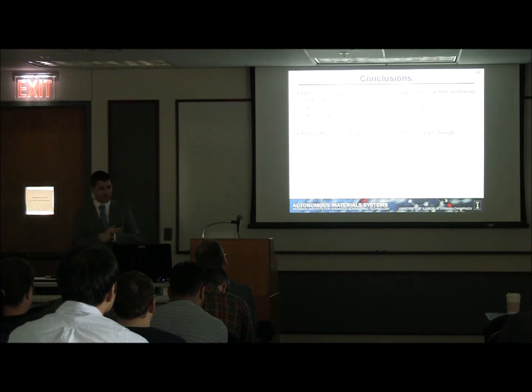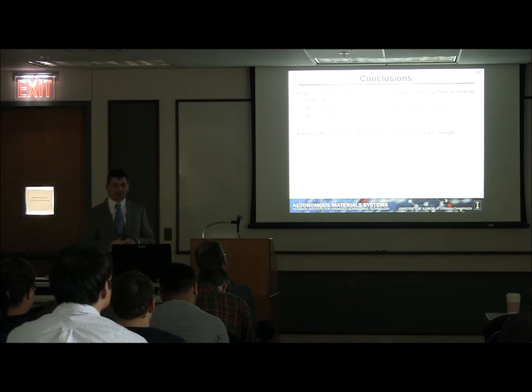So to conclude some of the impact studies, we demonstrated self-healing of impact damage in vascular fiber-reinforced composites. We had an average of about 47% of the post-impact flexural strength recovered, and about 83% of the post-impact modulus recovered on average. We also saw that the filling efficiency correlated with the recovery of post-impact strength, indicating that the more that we were able to fill, the better we could do.